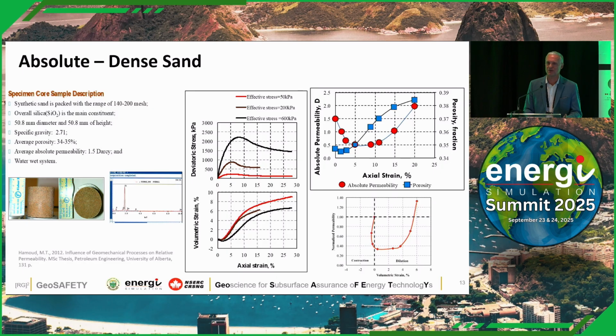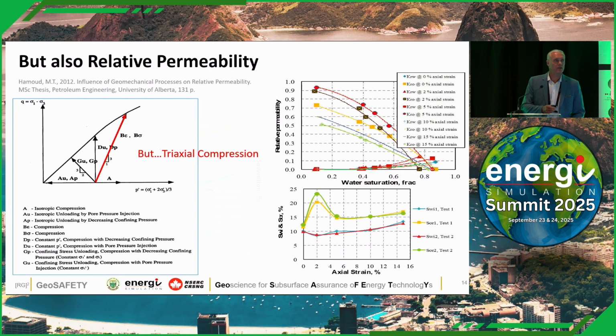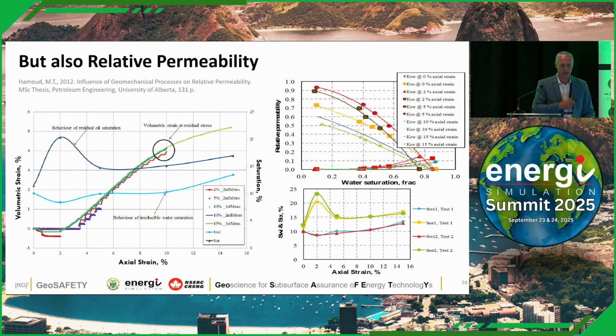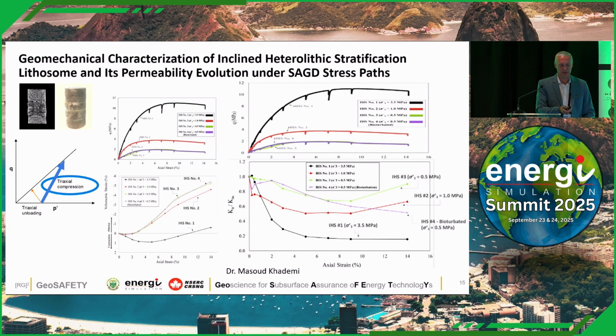Very rarely do you see this used in a simulation. Very rarely. Maybe a lot of people in here do it. The other thing that starts to impact this on a stress path is that the relative permeabilities change. The relative permeabilities shift. Endpoints shift. This is equally as true for CO2 as it is for this particular scenario, and so on. So those are important. All triaxial compression paths. There we go. Relative permeability shifts.